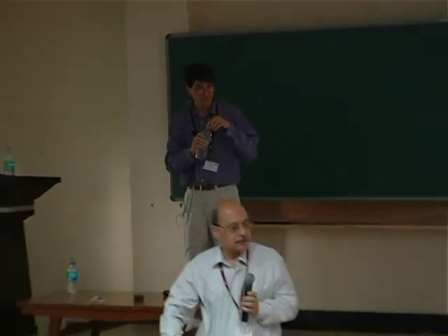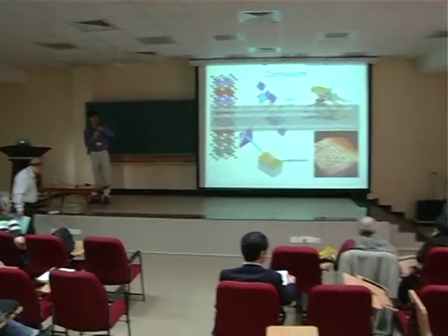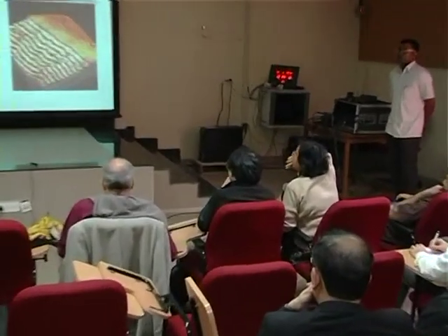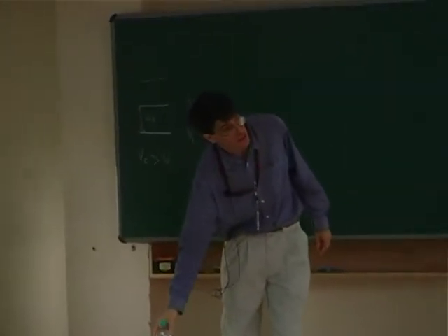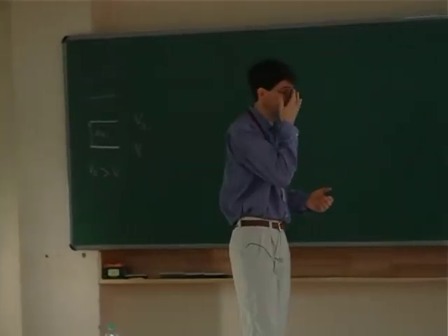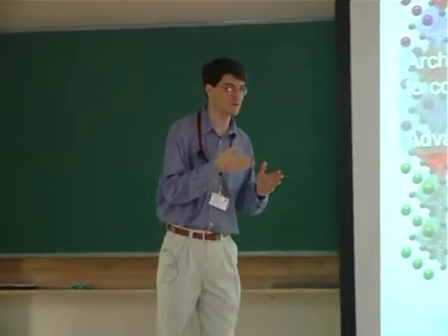Can I ask a question? By shining these photons when you were changing the structure, that should be a local structural change because your spot size is... Yes, it occurs within the laser spot. And actually, the mechanism in bismuth ferrite is not a thermal mechanism. We're able to figure that out.